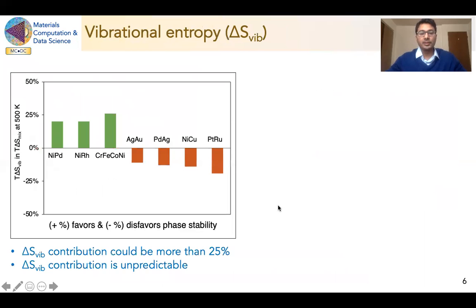Among all types of entropies, the contribution of vibration entropy is not straightforward. It can favor or disfavor the phase stability depending on the material. As you can see in this figure, the vertical axis is the vibration entropy contribution in the total entropy. Positive numbers mean it's favoring the phase stability, and negative numbers mean it's disfavoring the phase stability. There are some alloys, like these three equiatomic alloys, showing the vibration entropy is actually favoring the phase stability, and the contribution is significant. It can be up to 25%. Whereas for these four alloys, the vibration entropy is actually disfavoring the phase stability, and here also the contribution is significant. So the role of vibration entropy is unpredictable.